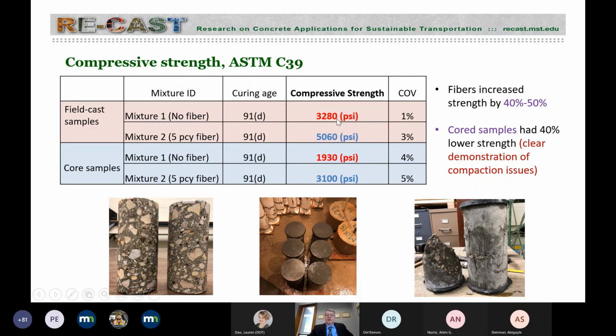So compressive strength 3,300 PSI, 5,100 PSI, no fibers, with fibers. So we could see that the fibers, which is unusual for fibers, improved quite a bit the compressive strength of the concrete. And they also improved quite a bit the compressive strength of the concrete from the core samples. But one thing we see here is a very large drop between the in situ core versus the field prepared samples. And that is, again, an issue with the consolidation of the concrete. So the CCP technology in this case gave us a very nice surface finish, but the consolidation in this case was not really adequate,